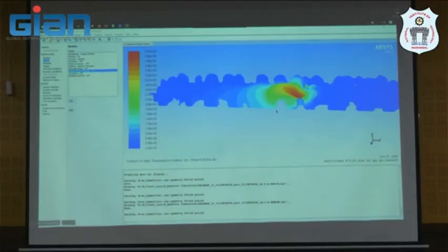What is the mesh size here? Mesh size is about, let me check, 4 micrometer. 4 micron. Not too small. I see. Probably in CA you may need a smaller mesh size, I think. Yes, we did some CA, so it will probably be 1 micron for CA, right? CA, I think, is 1 micrometer, or 64 times lower, so very high resolution.